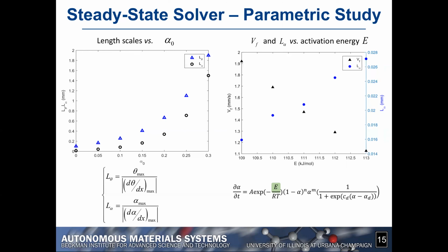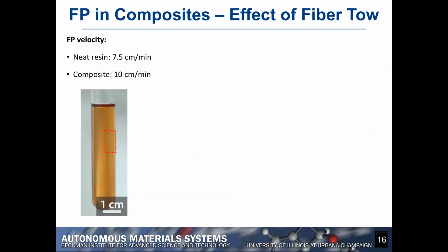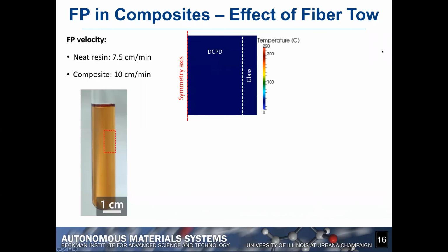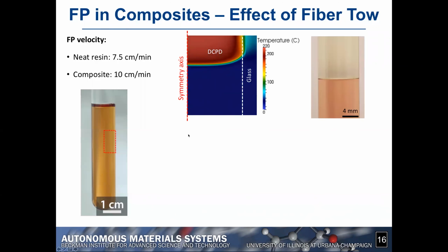What we are interested in is using this technology to make composite materials. Now, we expect that the presence of the fibers will have a strong influence on how the front propagates in this material system. If you look at the little part over here of DCPD, I can do the simulation of this particular system: this is a glass container, this is DCPD, this is an axisymmetric simulation, right? So what we see is that the front propagates in a fairly straight fashion, as observed experimentally.